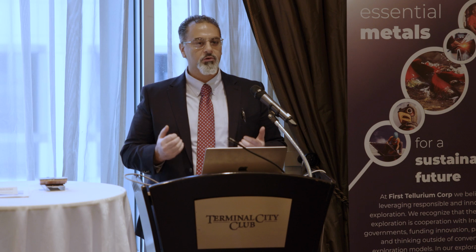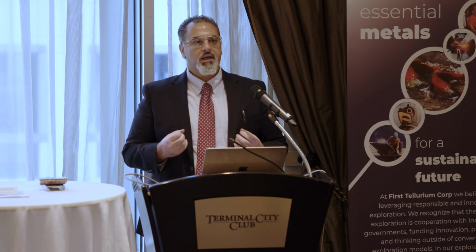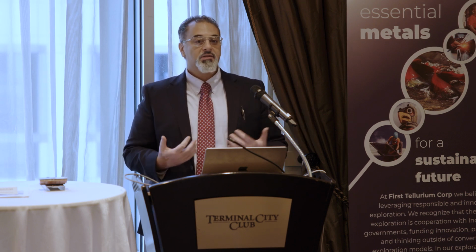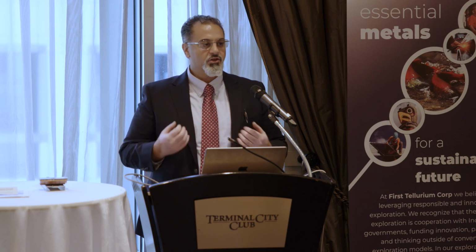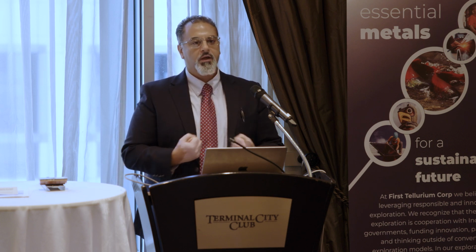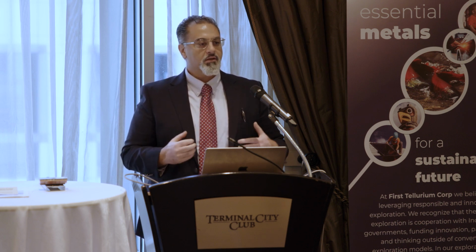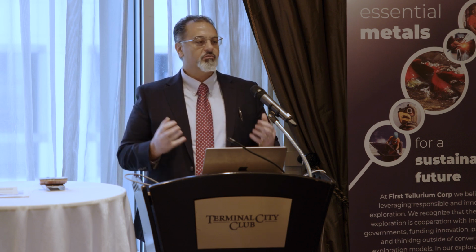The other advantage to this, and what makes it stand out compared to any commercially available product, is that we don't use powder metallurgy, we don't use metal powders. We actually cast the part from molten alloys. This gives it a much higher level of rigidity. It mixes the alloys much better. So it's not powder, it's actually molten metal fused together properly. And it just makes it more robust and more suitable for harsh environments, industrial environments, if it's going to be installed outside.